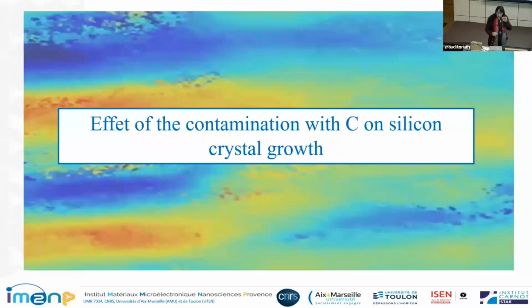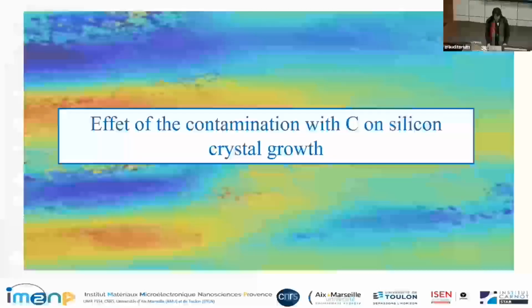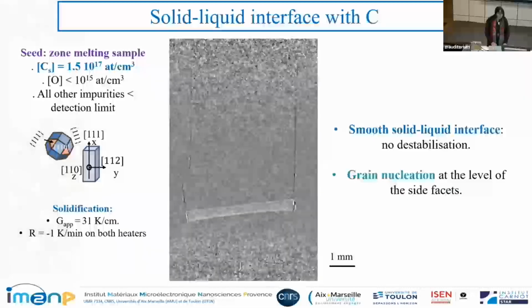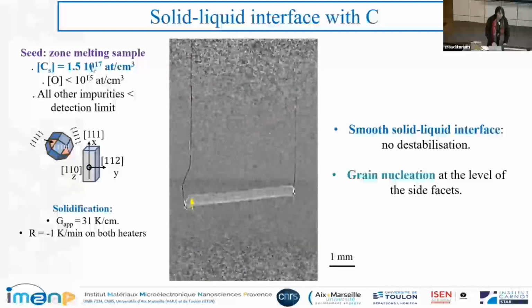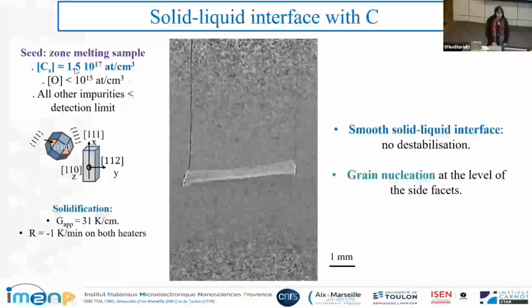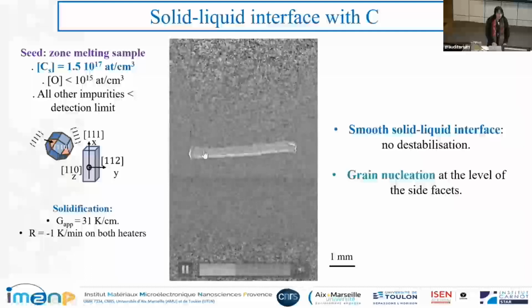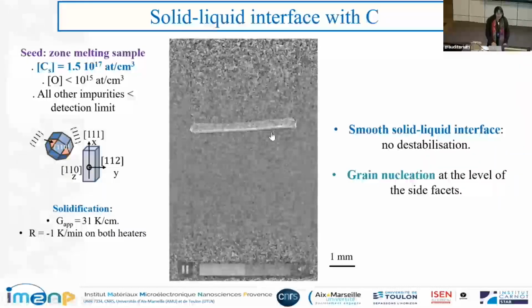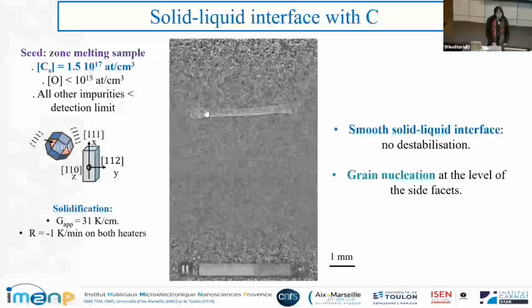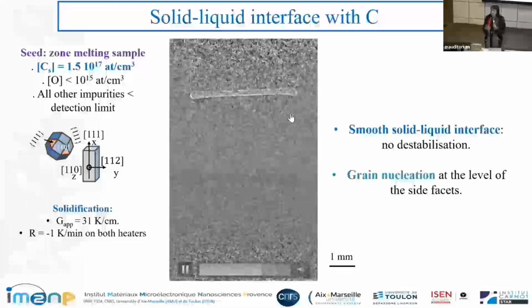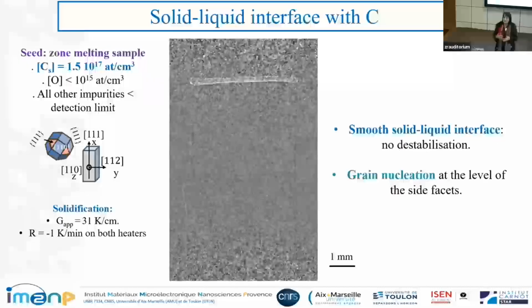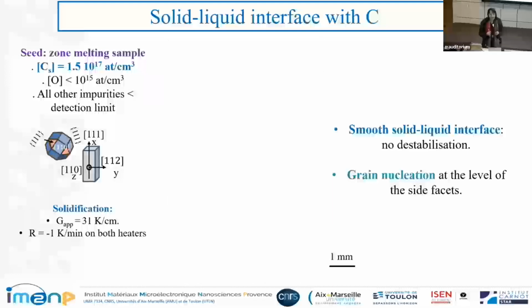So here we apply this to the effect of contamination of silicon with carbon, what happens during its growth or solidification. So we have a model sample with only contamination with carbon here, and we follow its solid-liquid interface during solidification. This solid-liquid interface in these conventional conditions of temperature gradient and cooling rate is smooth.